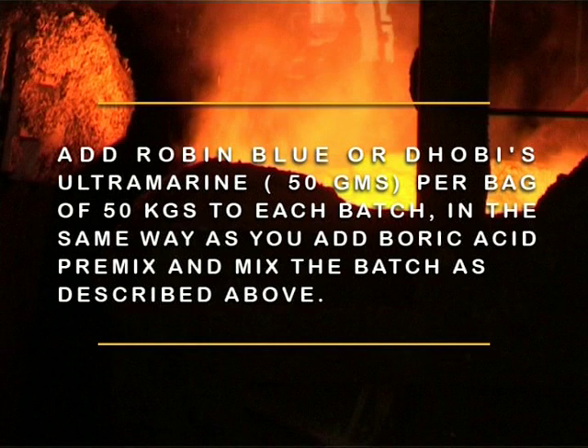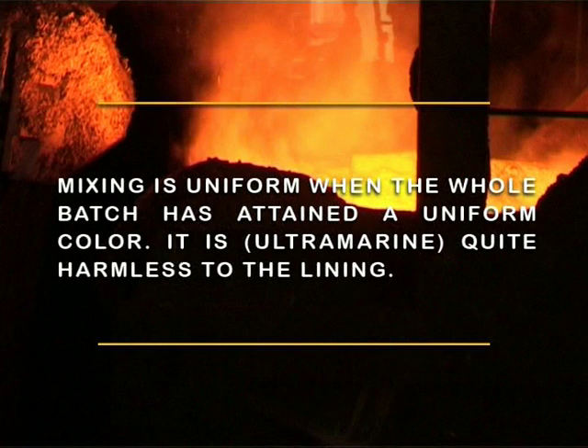Add ultramarine blue in powder form, 50 grams per bag of 50 kgs, to each batch. In the same way as you add boric acid premix, mix the batch as described. Mixing is uniform when the whole batch has attained a uniform color. It is quite harmless to the lining.